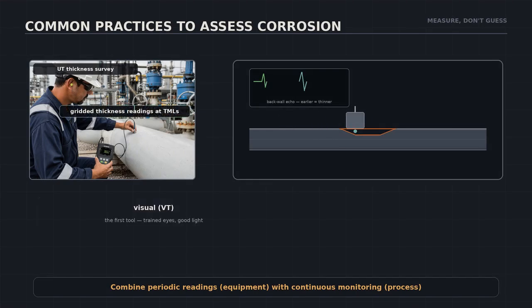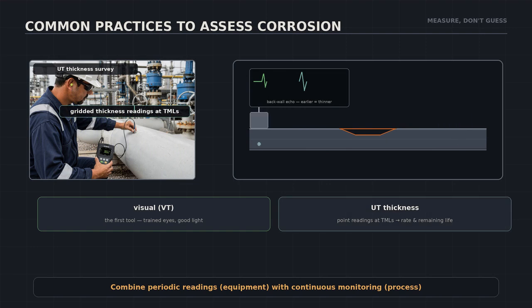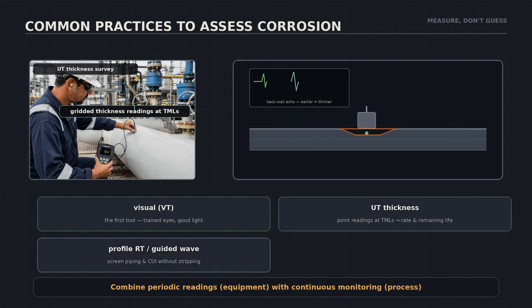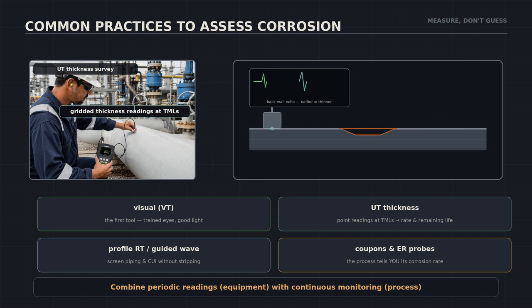The toolbox for assessing corrosion. Visual examination first. Trained eyes and good light still find the majority of problems. Ultrasonic thickness: grid readings at established thickness monitoring locations. The pulse echoes off the back wall, and a thinner wall answers sooner. Profile radiography and guided wave screen piping and insulated lines without stripping. And corrosion coupons and electrical resistance probes live inside the process, so the fluid itself reports its own corrosivity, continuously. Combine periodic readings on the equipment with continuous monitoring of the process, and very little can surprise you.